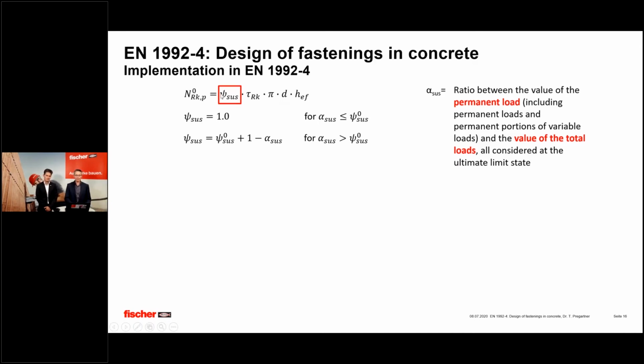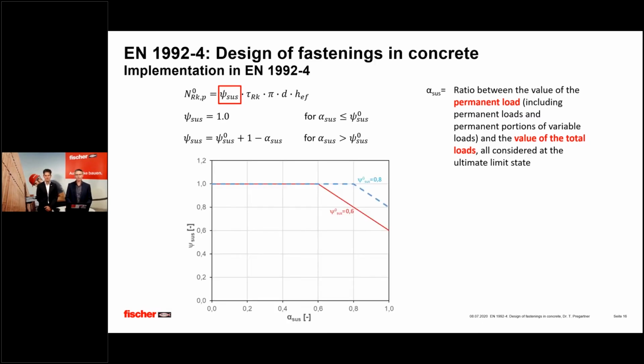And then there is, in EN 1992-4, this value psi sus. Psi sustained is a function of the value alpha sustained, where alpha sustained is the ratio between the creep-inducing permanent load and the value of the total load. So more or less, alpha sus shows you how big the part is of a constant load, which is always on your system, compared to the sum of permanent load and variable load.